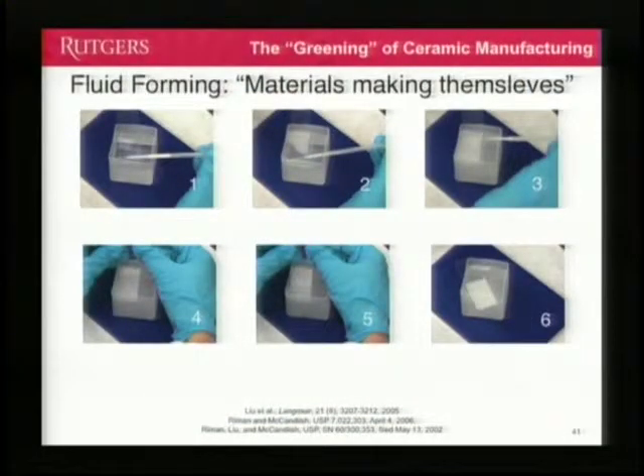Now we have these particles packing themselves into dense arrays, and if we put a glass slide into there, we can actually pull this material right off of the water to make a beautiful monolayer film. And so here's an example where we use industrial aluminum oxide and show we can pack these materials beautifully as a single layer of particles.